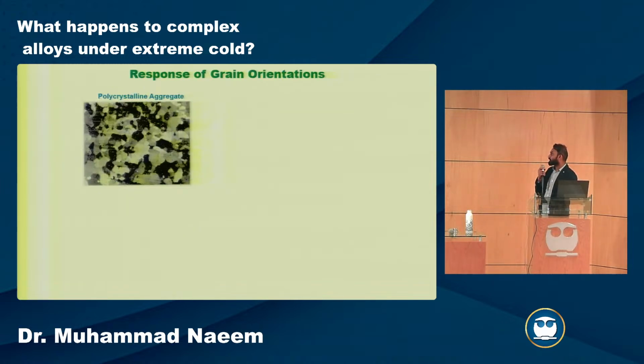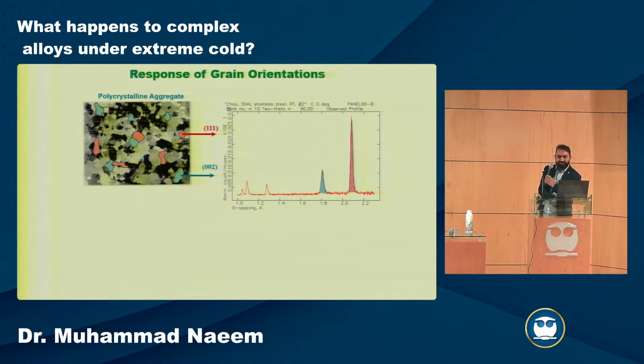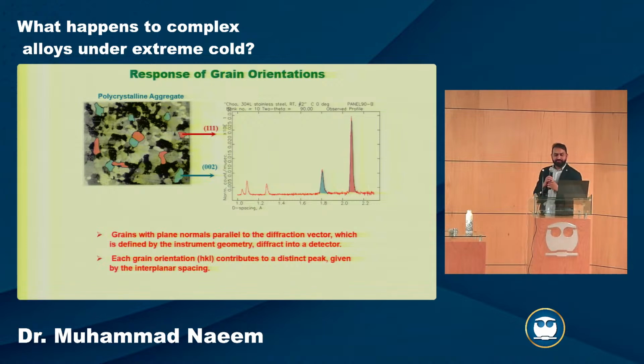Now this is a typical, say, polycrystalline material. I think this is 304. And here you have grains oriented towards, say, 111 and say 002. And how would that look on this peak? So you see the first peak, all these grains are contributing towards this peak. And then these blue ones contribute to the second peak. Right. So basically, by looking at this, we can get information about material behavior. And we can also look at different grain families' behavior during deformation by how the interplanar spacing changes.